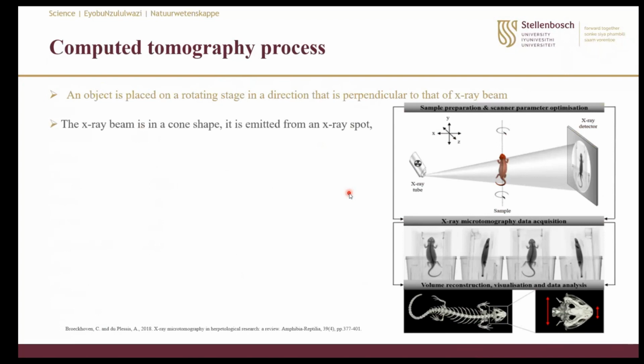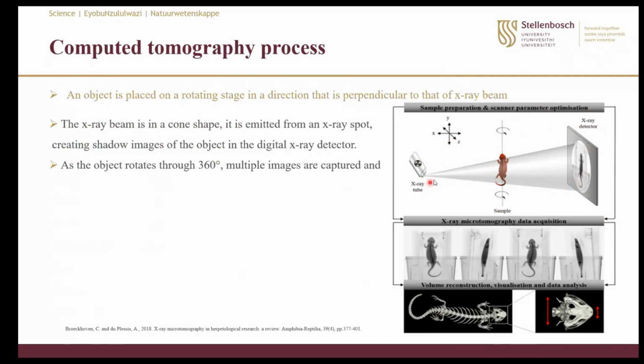So how this process takes place is that we'll be having a sample put in a rotation stage between a fixed X-ray source and the detector. And then the sample will be put in such a way that it is perpendicular to the X-ray beam emitted from the X-ray source. And then as the sample rotates through 360 degrees, the X-ray photons will be passing through and around the object, forming shadow images of the sample that is being scanned on the detector.